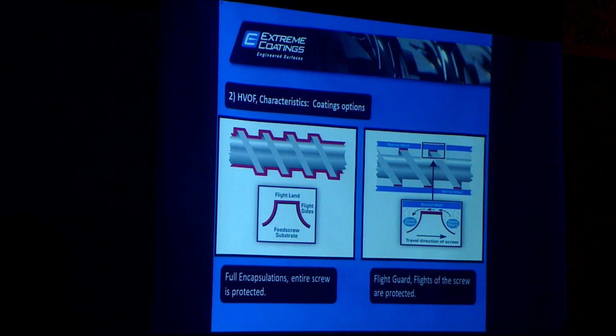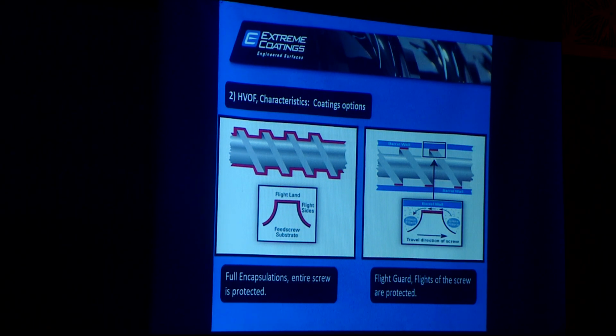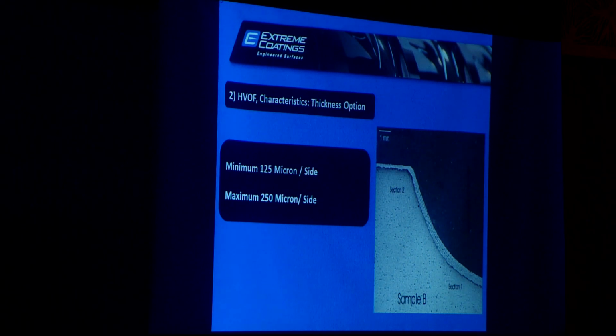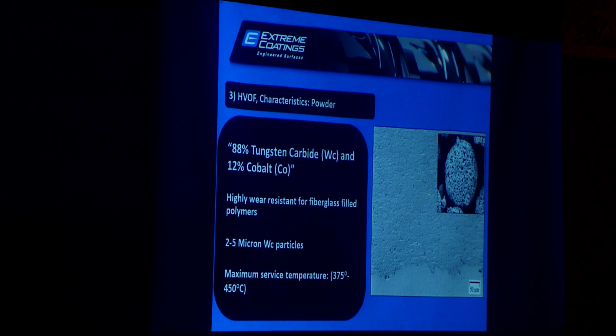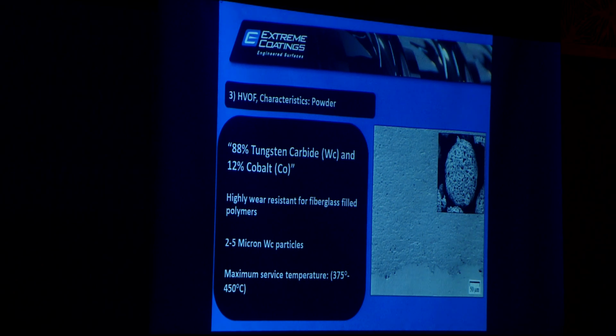We can put a layer of tungsten carbide of 250 micron or 125 micron, depending on the requirement, on the screw surface area. What is the benefit with our coating? The very best bimetallic which was available globally can put only 25 to 32% of tungsten carbide, while with our coating we are putting 88% of tungsten carbide on the screw, which itself can give 2 to 3 times the life of the bimetallic which you are using. Forget about the nitrided screw. Compared to a nitrided screw it can be 5 times, but compared to the globally best bimetallic screws available, this can give at least 2 to 3 times.